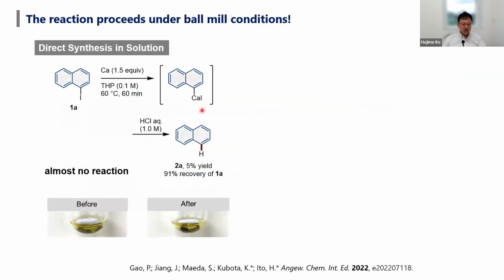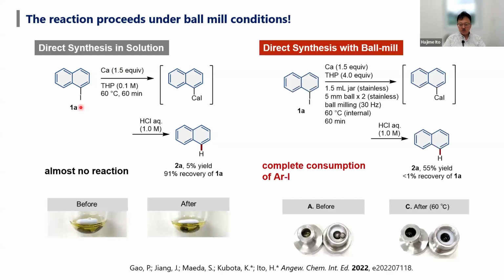So we tested the reaction of calcium and organic halide in solution, but as already shown in the literature, we could not find any good results just by mixing calcium and organic halide in solution.